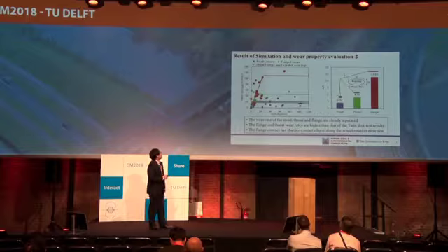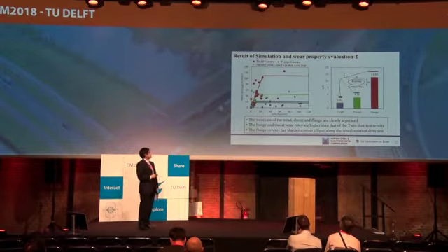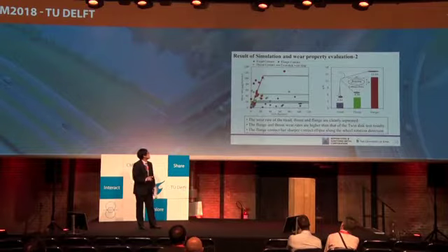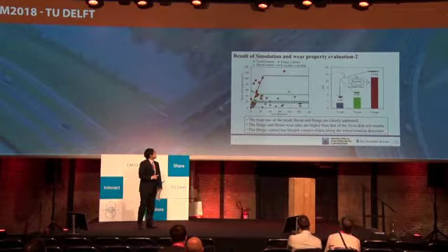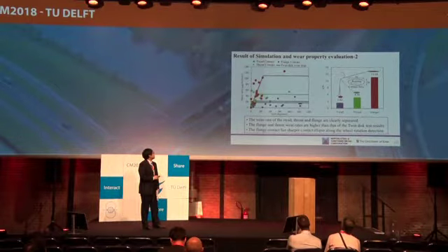From this figure, the wear rates of the tread, throat, and flange are clearly separated. And the flange and throat wear rates are higher than those of the twin disc test result.